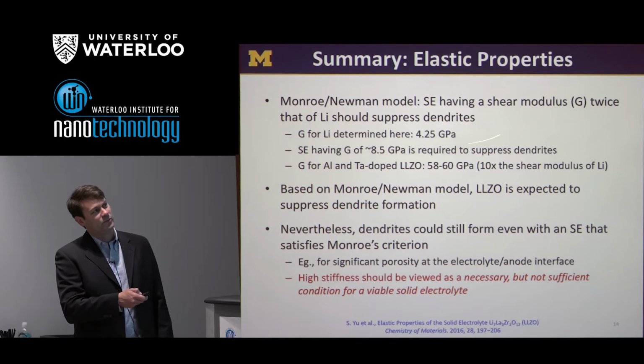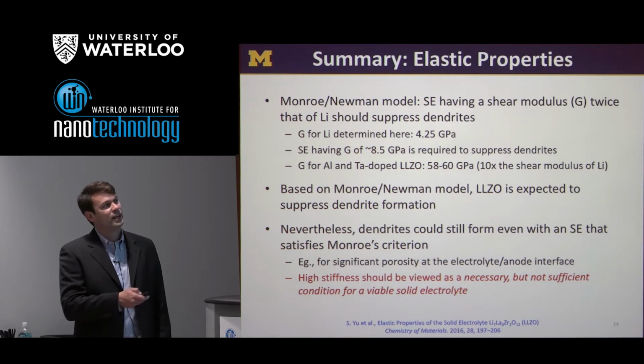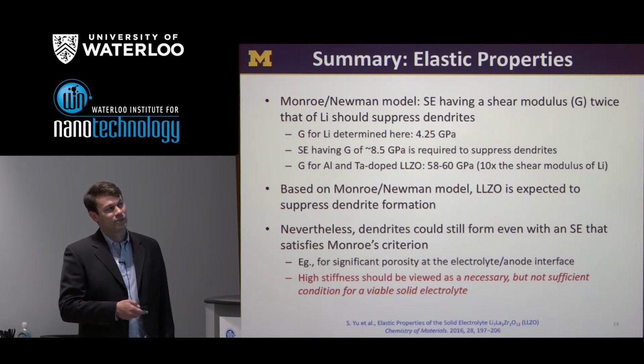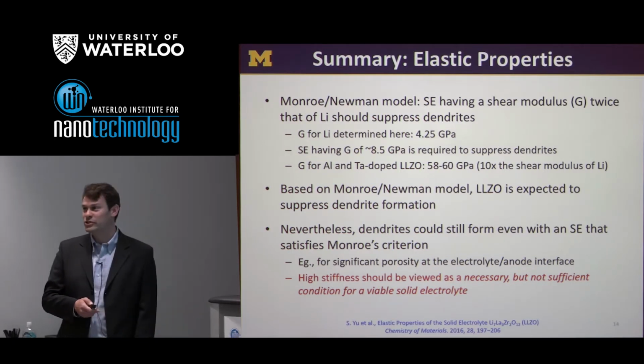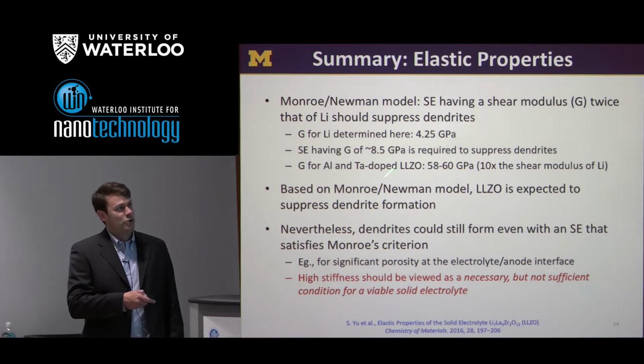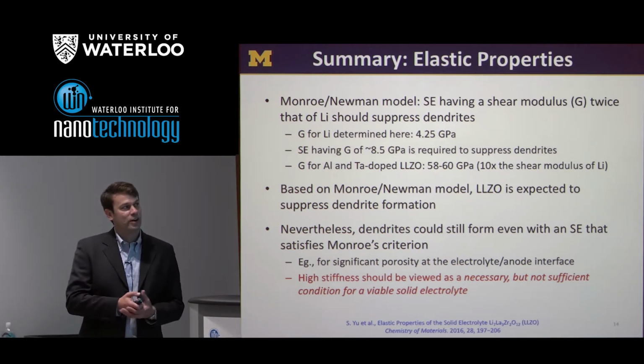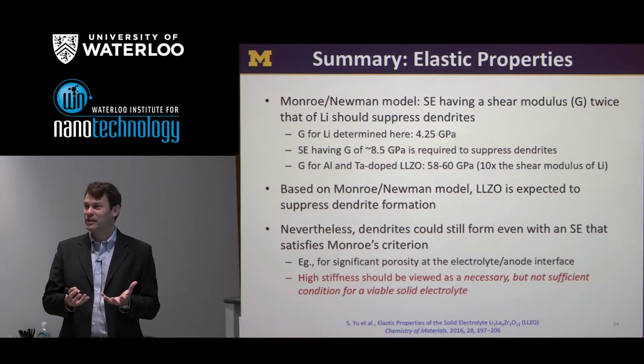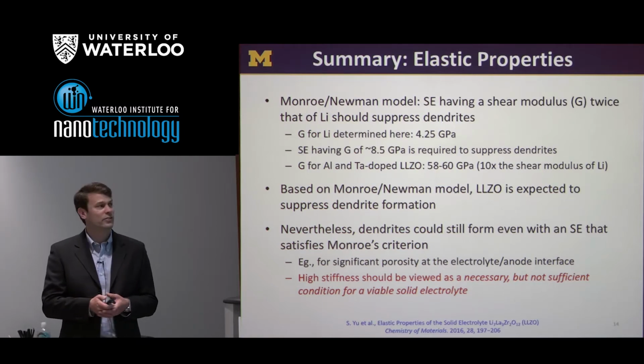So for lithium, we reported a value of 4.25. So 8.5 should be sufficient to suppress dendrites. And for LLZO, we're getting values of around 60. That's about 10 times the shear modulus of lithium. So in principle, we should be able to check the box. Monroe-Newman says that this is a stiff enough solid to suppress dendrites.